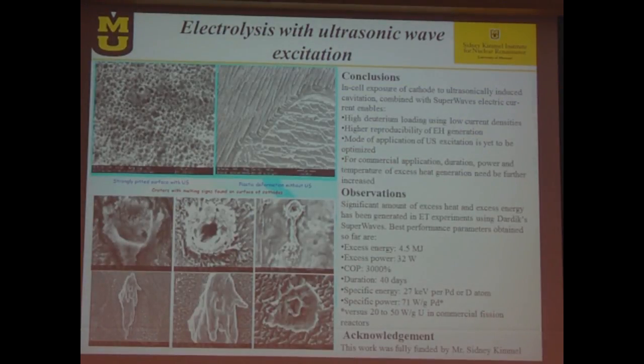So dynamics is important, and this is how the surface looks like. You remember the labyrinth structure or labyrinth surface? It's actually a pitted surface, like millions of hammers hitting the surface and creating these funny gliding shapes, gliding surfaces due to the stresses developed in the lattice while being loaded. And in fact, we are able to load into a very high loadings with super waves, but with very low current densities, unlike other electrochemical processes. I'm talking about less than 6 milliamps per square centimeter, getting all the way to close to unity.